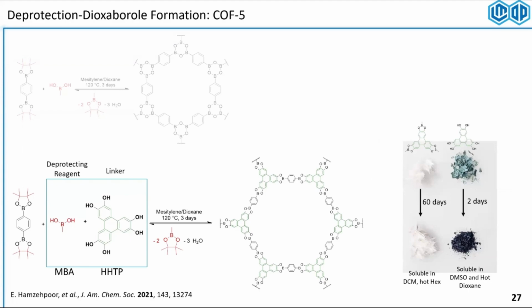And this hexahydroxytriphenylene molecule, which has 6 hydroxy groups on a pi-conjugated core, is very insoluble, highly oxidative and unstable on the bench. Essentially, even if you buy it from companies, you open it in the glove box, it's already gray. And if you just put it on the bench for 2 days, it polymerizes and oxidizes into different species. So I started thinking, why not connect the deprotecting agent, this methyl boronic acid, to the catechol moiety? We protect our catechol from all these oxidations. We turn it into a single precursor that can get the pinacol off for us through this methyl boronic acid. And this hexahydroxytriphenylene would be able to go and link the precursor for us.